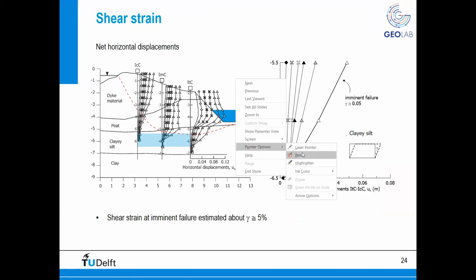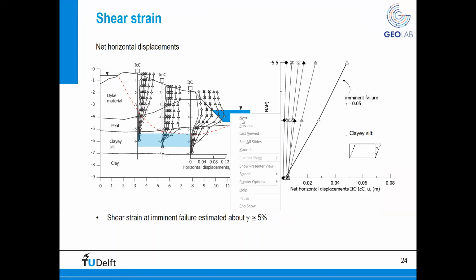If you remember before, I was trying to suggest that you keep in mind the profile of the water content in situ. So you can clearly see that the profile of the water content somehow provides an indication of the failure surface. You see here that we reconstructed the shear strain at the incipit of failure. And by looking at the lateral displacement inside the clayey silt layer, we were able to estimate that just before failure, the shear strain was about 5%. So 5% was the shear strain inside the clayey silt layer that brought the sample to failure.